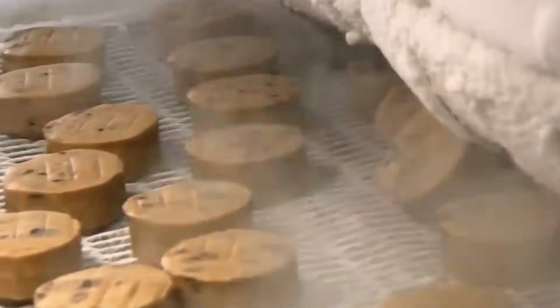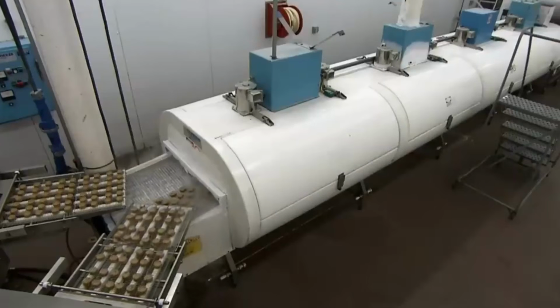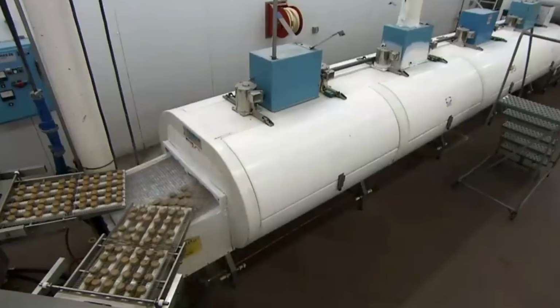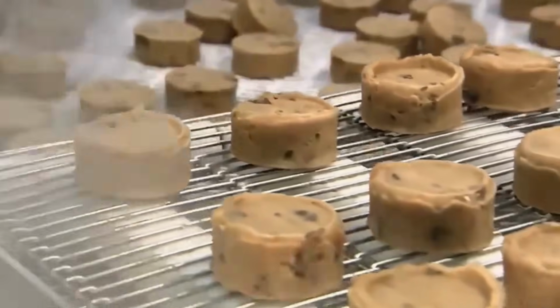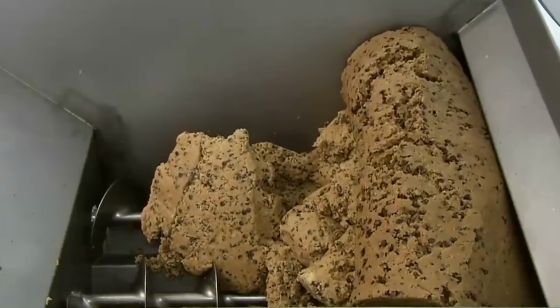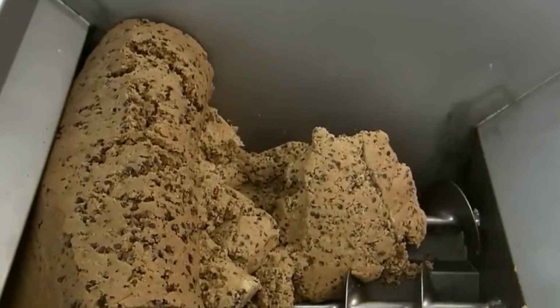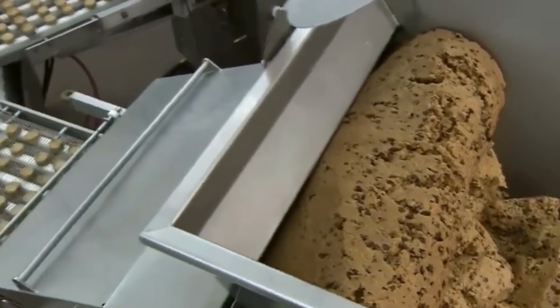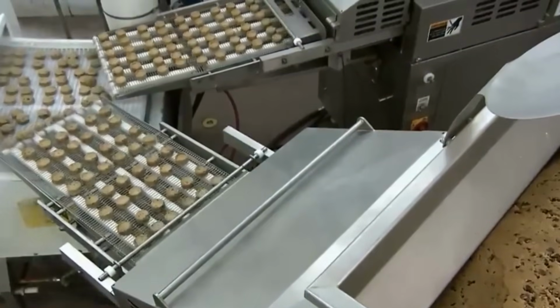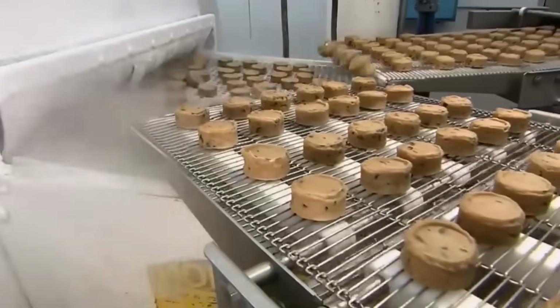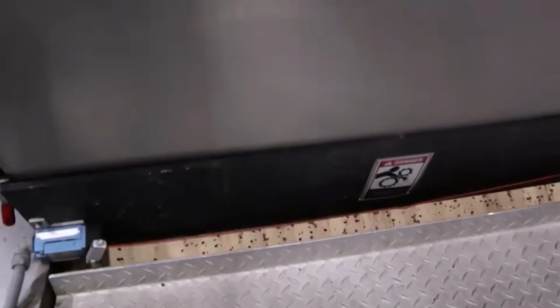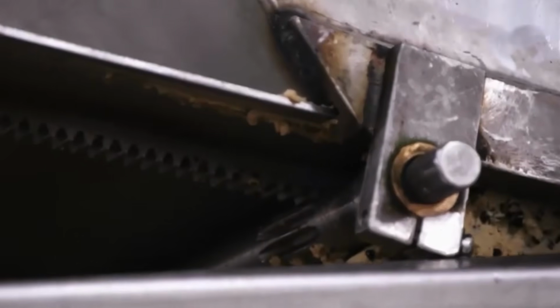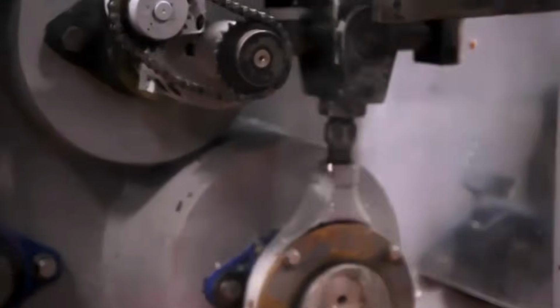Optical sensors monitor spacing, alignment, and shape, correcting for drift in real time. For wire-cut lines, dough is pushed through nozzles and sliced cleanly by a fast-moving wire as the band advances. For rotary molded formats, dough is pressed into engraved molds on a rotating drum, then released onto the band using a flexible scraper blade. Shape, weight, and chip distribution are confirmed by an overhead vision inspection system using laser profiling and high-speed imaging. Defective pieces are automatically rejected via air puffs or diverter gates.